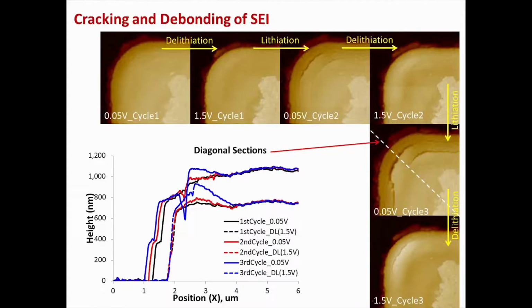Another thing which is very clear from this height profile and these AFM surface topographs is, if I take a diagonal cross section and plot the height profile, what you can see is the cracking behavior, and there is some kind of surface SEI lifting. These edge sides, which show some kind of white height behavior, white color, are lifted. So there are both cracking and delamination sections present here.